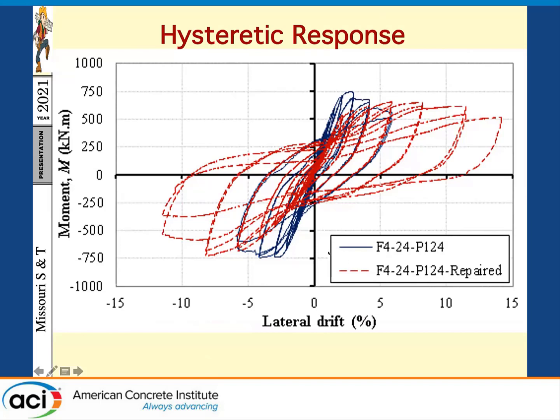So as you see here, the repair was not able to achieve the full capacity on one side. The difference was probably about 10%, but on the other side, we reached the full capacity of the original column. What's more important is really, if you look for the red loops over here, the repaired one, we achieved very much better energy dissipation and higher displacement.